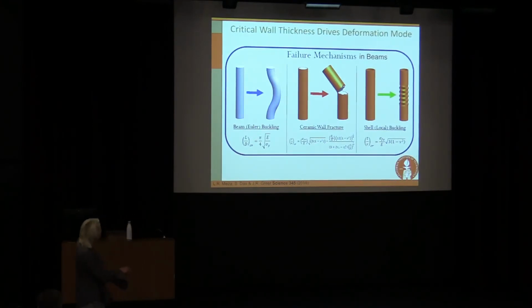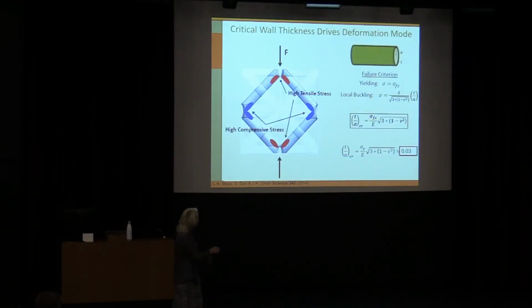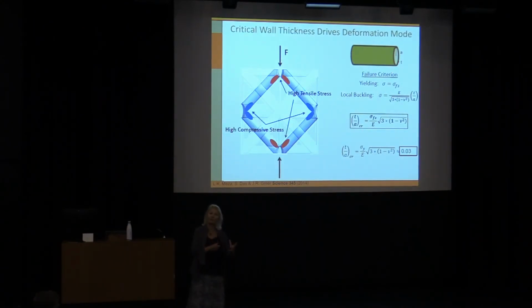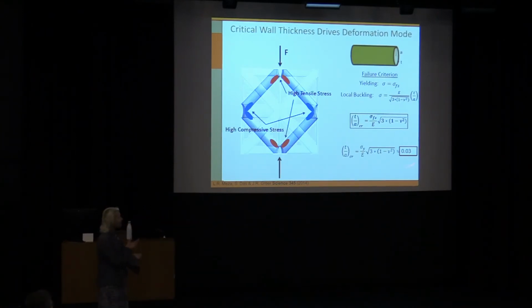Well, so it turns out that hollow beams, which is what the key element is in most of these architectures, undergo a process called shell buckling. So that's an elastic instability that is what might be the mechanism for what allows the structures to recover. Well, it turns out that for these kinds of deformation processes, you need to meet a particular criterion. So if you have a beam whose thickness is T and whose radius is A, and you compress it, for it to be able to undergo shell buckling prior to failure, we have to have a certain T over A critical ratio. And so for this particular material, for the alumina, that critical ratio turns out to be something like 0.03.